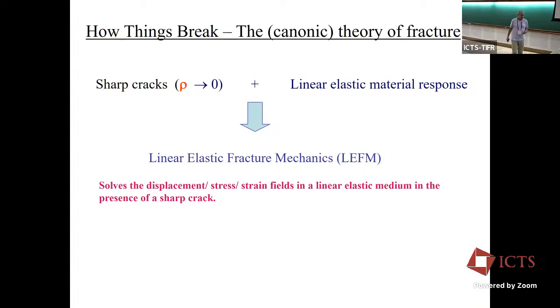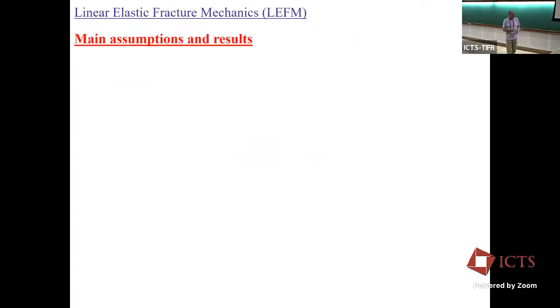And I won't go through it here, but the theoretical background is that you have wave equations in the bulk, two wave equations, because we have shear and compressive waves. And they're only coupled at the boundaries. So all of fracture, if you actually solve the problem, is given by solving two uncoupled wave equations that are coupled on the boundary. And the boundary is very non-trivial. We have free stresses in back of the crack because it's broken, so there aren't any stresses in its wake. And there's something called mixed boundary conditions. In front of the crack, you have a displacement condition, how stretched it is. And solving that will give you what I'll tell you about in a minute.